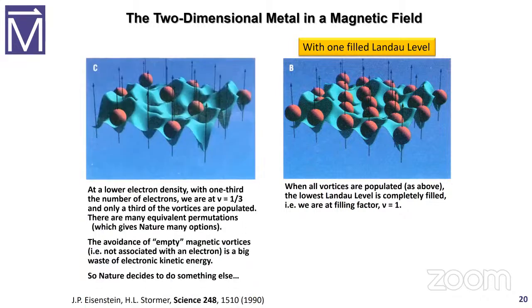All right, now let's lower the electron density to 1/3 the value. So now 2 out of every 3 of these minima is empty. So that is a candidate for what's happening at 1/3 filling. You've only filled 1/3 of those pockets. But there are many permutations. Nature could put the electrons wherever it wants without violating the Pauli exclusion principle.